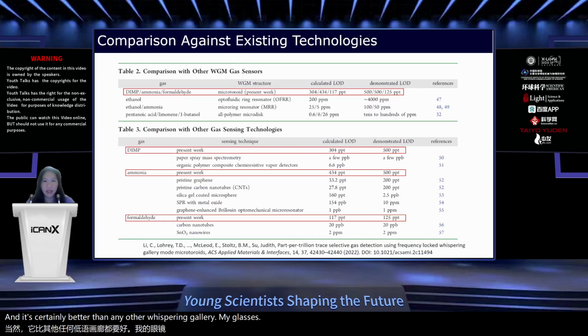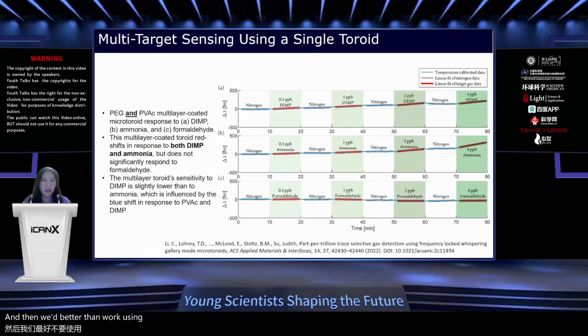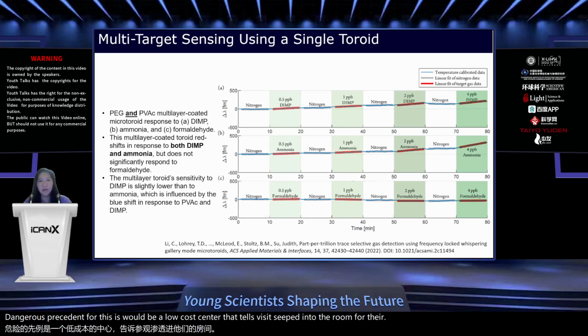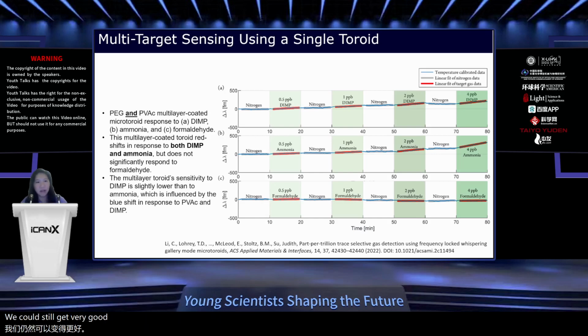Okay. And then we've also done work using multi-target sensing. This is where we have interest in, for example, just a sensor that can tell you is something dangerous present in the room. So this would be a low-cost sensor that tells you, is it safe to enter the room, for example. So what we did was we do a mixture of these polymer coatings, we put them on the toroid, and then we can still get very good trace detection using mixtures of polymers on the surface of our sensor.